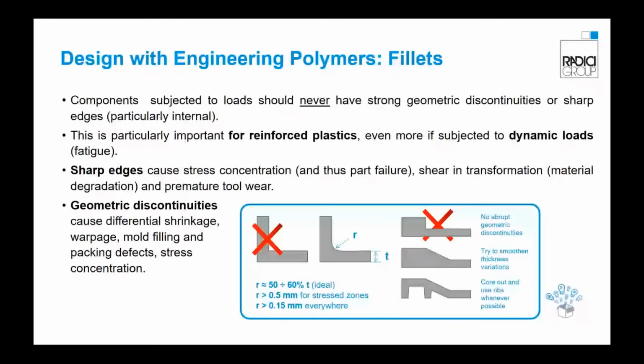Another thing to avoid in the design with engineering polymers are strong geometry discontinuities or sharp edges. For reinforced plastic materials, the geometry discontinuities cause differential shrinkage, warpage, and mold filling defects. And when the parts are subjected to a load, these sharp edges, particularly the internal ones, cause stress concentration and then a high risk of premature part breaking. Hence the use of fillets in order to avoid these geometric discontinuities.